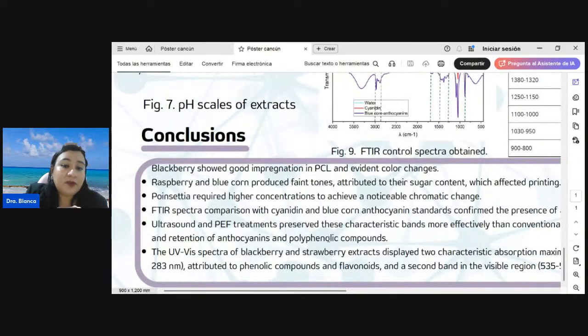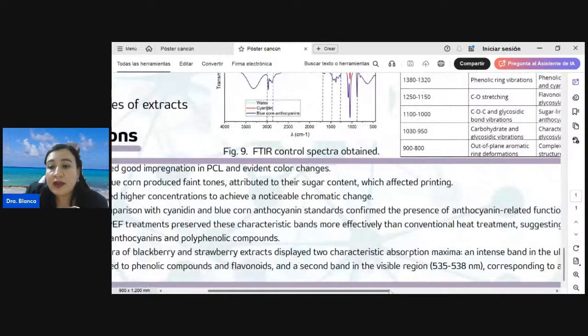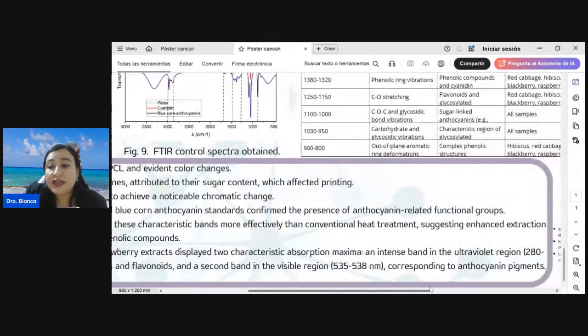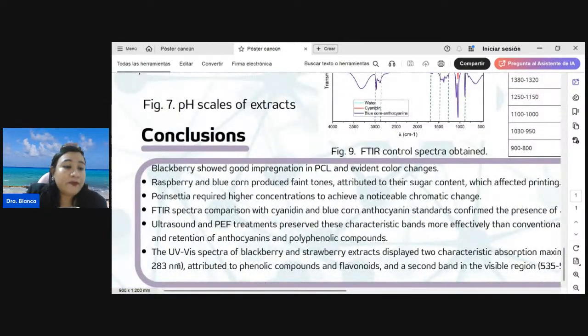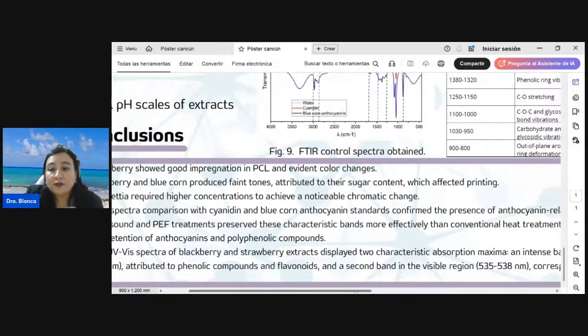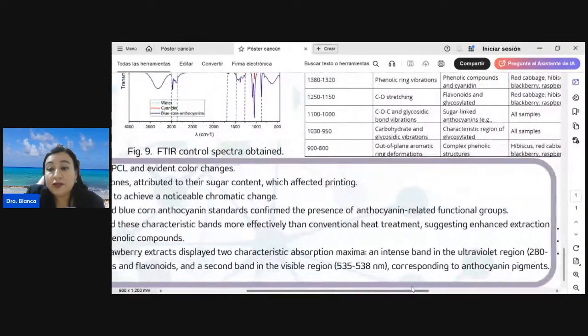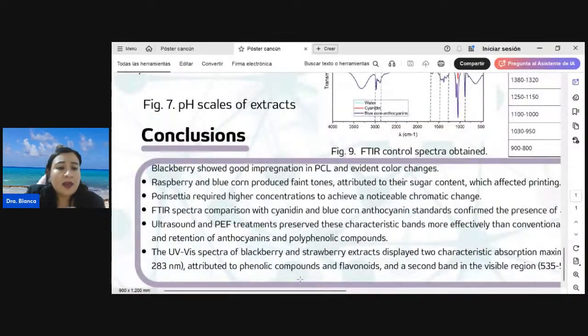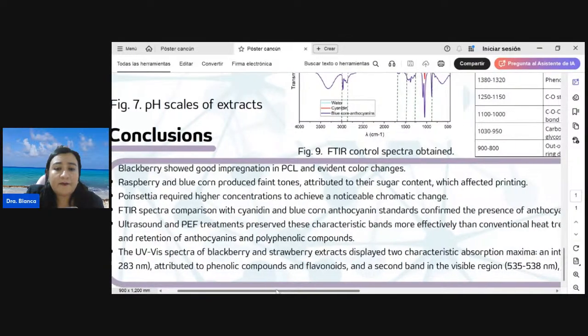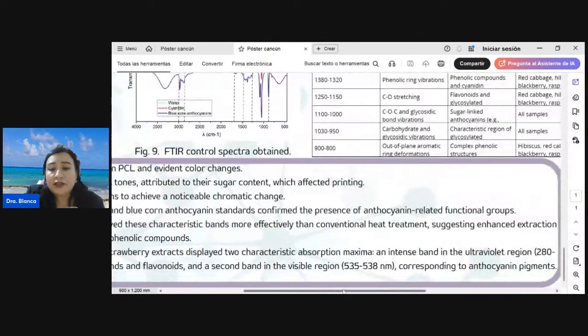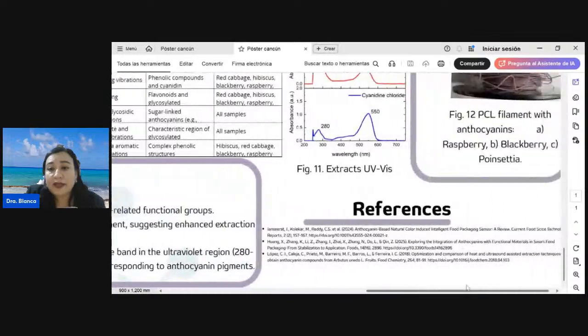Ultrasound and PEF treatment preserve these characteristic bands more effectively than conventional heat treatment, suggesting more efficient extraction and retention of anthocyanins and polyphenolic compounds. The UV spectra of blackberry and strawberry extracts display two characteristic absorption maxima: an intense band in the ultraviolet region, attributed to phenolic compounds and flavonoids, and a second band in the visible region corresponding to anthocyanin pigments.